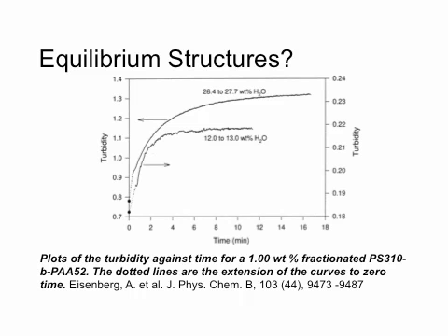So I have a certain system that's stable. I add a little bit of water in this case, and the system just takes time to redistribute. And it depends on the dynamics. So for these molecules, you have to wait about 10-15 minutes before you reach the next state. For SDS molecules, which are way smaller, you can imagine that that goes way quicker. Yeah? So the equilibrium structure is a function of lots of things.